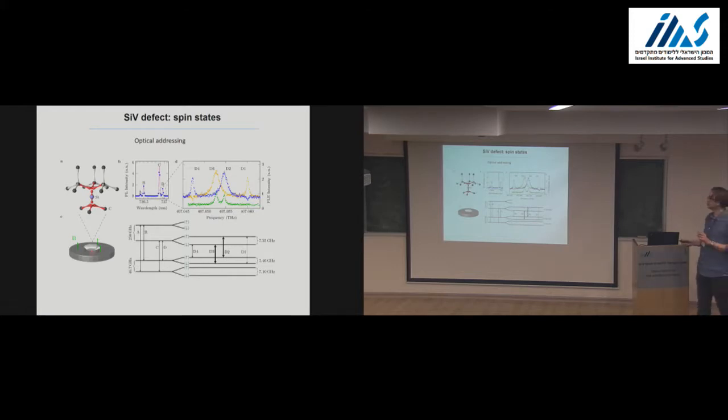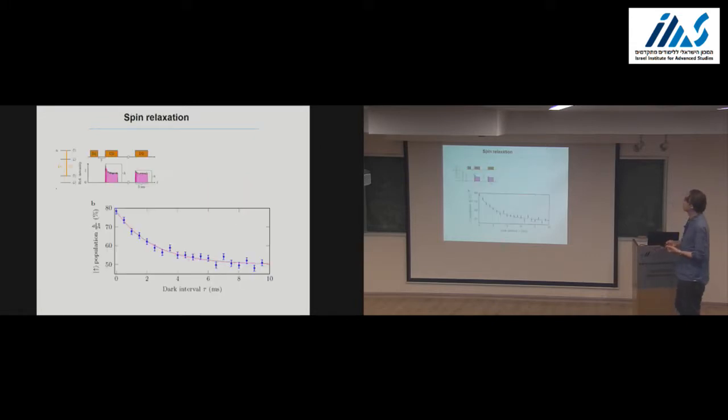You again can control the state of individual atoms by making an optical pumping cycle, placing all the population in one of the spin sublevels, and now look at how long the spin state lives. So it's now a spin state, not the orbital state, and the decay time is significantly longer. It's a millisecond time scale essentially as a decay at 4 kelvin. So not every flip of the orbital leads to a flip of the spin state. So the spin states are living longer, and this already creates an interesting system, because the spin states are significantly longer living than the orbital states, a millisecond.